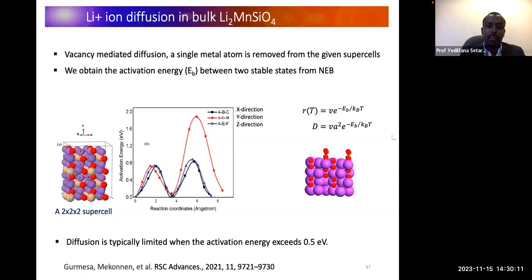Then we consider as much as possible we can do in all the X, Y and Z directions, and we found the profile, as you can see in this graph. Most of the channels, most of the diffusions, are below 0.8 electronvolt in activation energy, but one of them is actually high, so diffusion in that direction is totally limited. It's not easy for lithium to diffuse in that direction, because the barrier is extremely large. Okay, even the others are large.